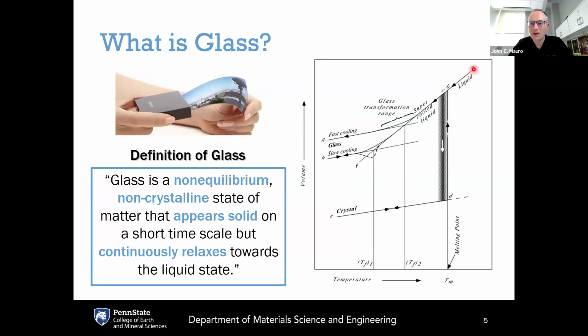So if we start here at this point A at high temperatures and high volume, let's suppose this is the equilibrium state here. What normally happens is that when you cool a liquid and it gets just below the melting point of the corresponding crystal, then there is a thermodynamic driving force for the liquid to crystallize. It will undergo a first order thermodynamic transition, which involves a discontinuous change in the volume and the enthalpy and the entropy. And in order to stay in equilibrium, the liquid will crystallize, and then continued cooling of the crystal would lead to shrinkage following its thermal expansion coefficient.